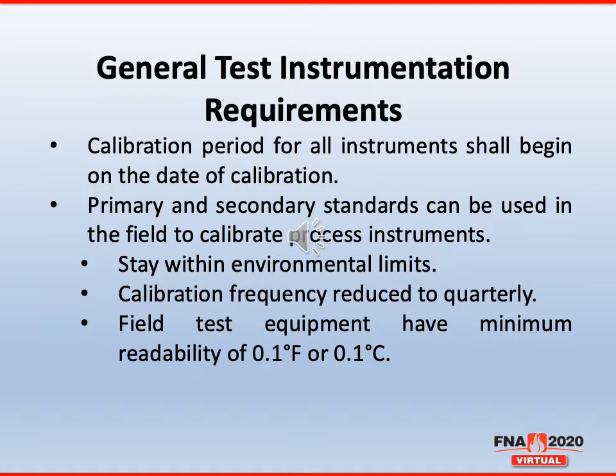Lastly, field test instruments. These would be your instruments that are used to do system accuracy testing or calibration of the instrumentation on the furnaces, or your temperature uniformity survey recorder data acquisition. They now have to have a minimum readability of 0.1 degree Fahrenheit or 0.1 degrees Celsius. Some of the test instruments out there that are being utilized now, once the readings get above 1,000 degrees, they lose their decimal point. So that's one change that people should be aware of when it comes to your test instrumentation.